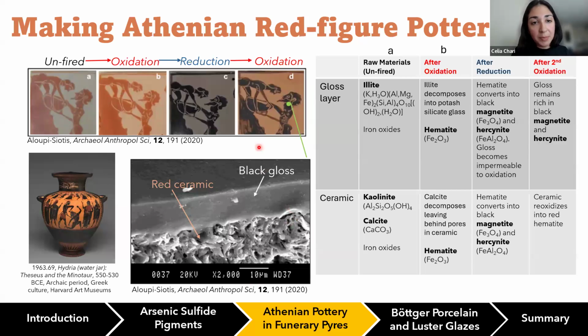In the second oxidation step, the temperatures are much lower than the reduction or the previous oxidation step, so they never quite reach temperatures high enough to soften that gloss. And that gloss remains impermeable to oxygen diffusion and traps those black iron oxides. Whereas with the ceramic, the body is still quite porous. So oxygen can diffuse into the substrate, reoxidize those iron oxides, creating a stark difference between that black layer and the red substrate. And that's really how red figure is made.